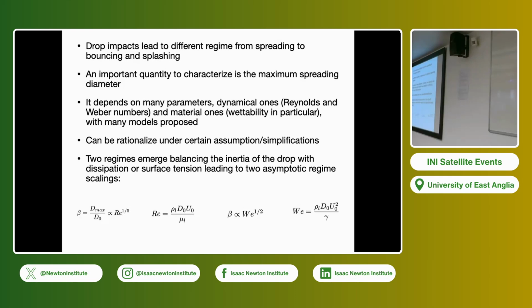and the thickness of the liquid layer decreases as a function of time. But at the same time, if you consider viscosity as a boundary layer that grows from the substrate, there is a time at which the viscous boundary layer will meet the free surface. And if you just do this balance, you also get Reynolds to the 1/5, which is probably a better way to understand where the maximum diameter is. So this is a competition between the viscous boundary layer and the free surface, and when they meet, you get Reynolds to the 1/5. The other limit is maybe easier to understand.